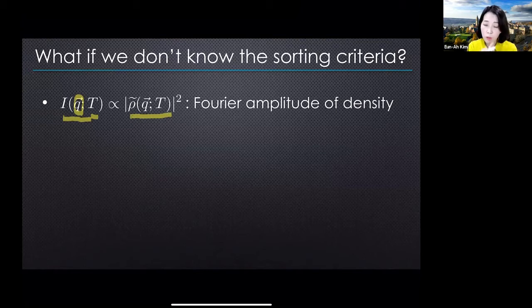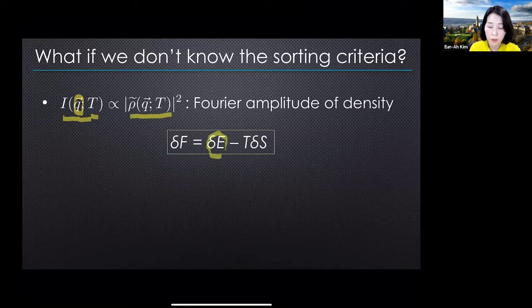And if I want to develop a tool that can have a broad applicability, I do not want to design this based on some specifics of a particular system, but I want to rely on some fundamental principle. And the fundamental principle that we thought about was that no matter what the Hamiltonian is that determines the energy, there is always a competition between the Hamiltonian, or energy, and the entropy, and what's controlling the balance is temperature. So as you lower the temperature, the desires that are driven by the underlying Hamiltonian interactions will show up as one type of temperature dependence. And random noise would have a different type of temperature dependence.